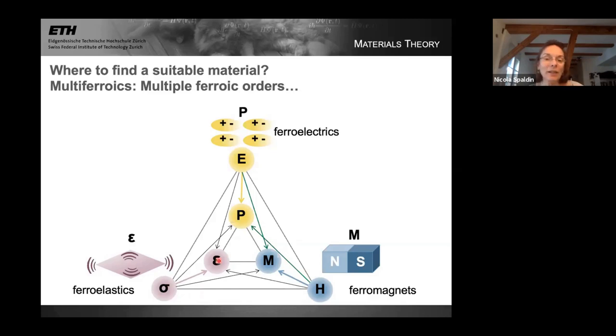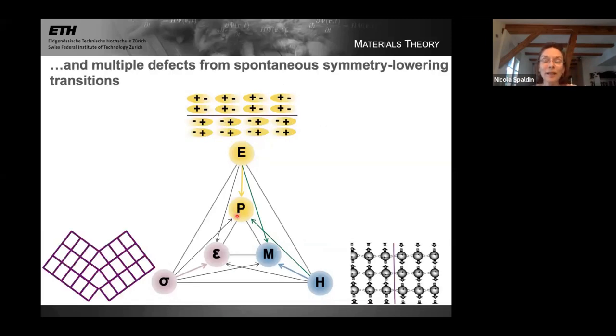And so I had been interested in multiferroics for many years, actually because associated with the combined properties, for example, the combination of polarization and magnetization, are also these cross couplings that I've shown in the green arrow here, so that one can, with an electric field, control the magnetic properties, or with a magnetic field, the electrical properties. For this project, actually, that's not what we're interested in. What we're interested in is that associated with each of these ferroic orders is a spontaneous symmetry breaking phase transition and the formation of a defect. So we looked earlier at the example of the formation of a domain wall in a ferromagnet. Likewise, in a ferroelectric, the intersection between electric dipoles usually forms a domain wall. In a ferroelastic material, one has a twin boundary between different orientations of the deformation. And so a multiferroic material gives us many options for searching for a symmetry lowering phase transition that has the appropriate symmetry.